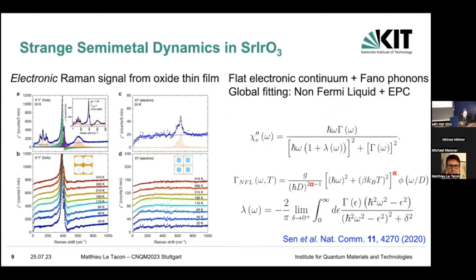These are some spectra that we obtained. So this is the intensity as a function of energy. The typical Raman spectrum looks quite complicated. There are a lot of phonons, but most of them are normal phonons with a normal Lorentzian line shape that you can easily subtract. And you get two modes here, which are a bit more annoying because they show a strong asymmetry. This asymmetry comes from a coupling of those phonons to a continuum of excitations, typically an electronic continuum. Most of the time, we know that there is a continuum just by looking at the shape of the phonon, seeing that there's a funnel. But in the case of the iridate, with great care, we could actually measure that continuum here. And so we could see it, and we could actually fit it.